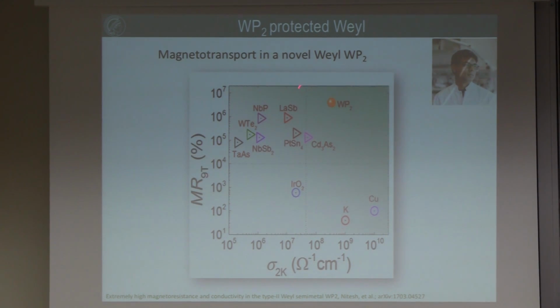So simply to put it in a bigger context, these are Weyl semi-metals, Dirac semi-metals. These are the highest conductivities found in any material, so sigma. And so you see tungsten phosphide, a single crystal grown from materials bought from Aldrich and not taken care of in any specific way, there was no treatment. It's already really amazing, and this is unique in tungsten phosphide too.